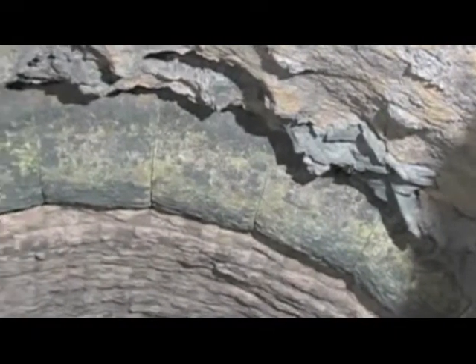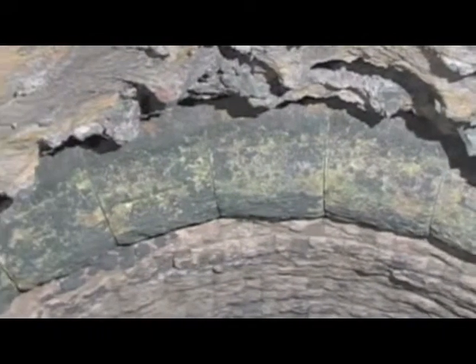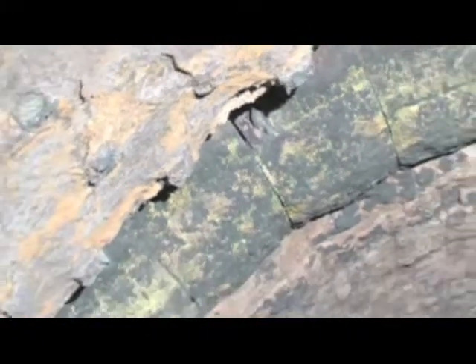After opening the kiln hood, some wear on the height of each block was noticed. Just a few locations were broken off where the block had come in contact with the kiln hood. The face of the blocks is where most of the wear is found, requiring installation of a new set. Over the past 5 years, many nose rings have been installed and come out of service between 18 and 48 months service cycles.